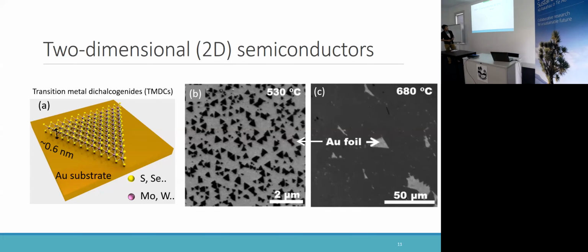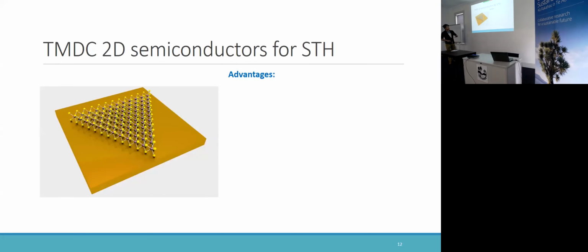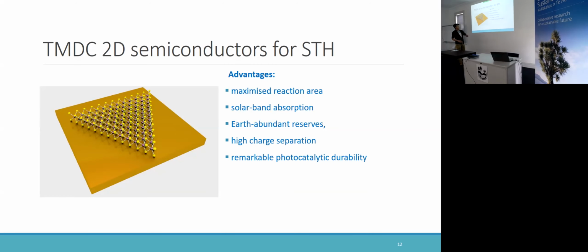So if we use these 2D semiconductors for the PEC system, it has a lot of advantages. The first is that it has a maximized reaction area. Even if we use bulk semiconductors, the photocatalytic water splitting reaction area is almost the same as the 2D materials, because the water molecules cannot penetrate deep into the semiconductors, and the reaction can only happen at the surface. So the reaction area is very, very big.